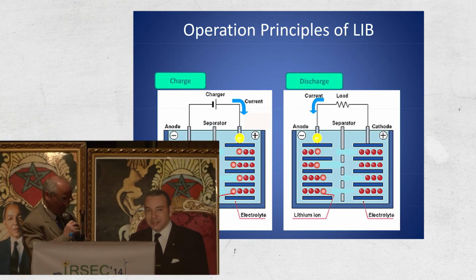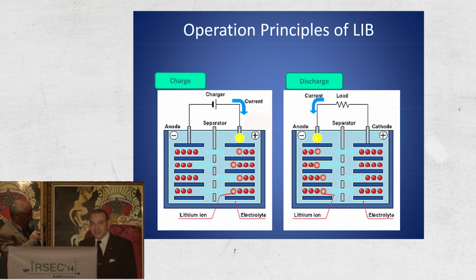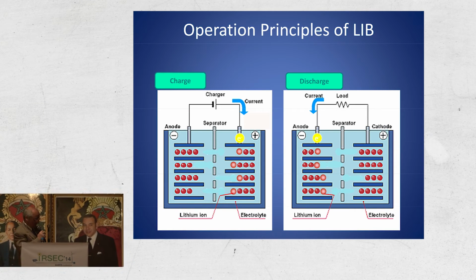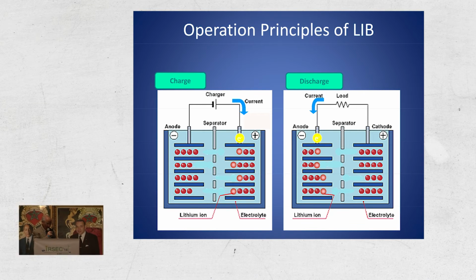So this operation can repeat itself, and the system is working nicely, as long as, again, there is no break-in in this separator, there is no direct contact here, and also the lithium ions, when they are exchanged between the anode and the cathode, go to the right side in the electrode. If they make mistakes, and mistakes can happen, then you are losing your capacity.